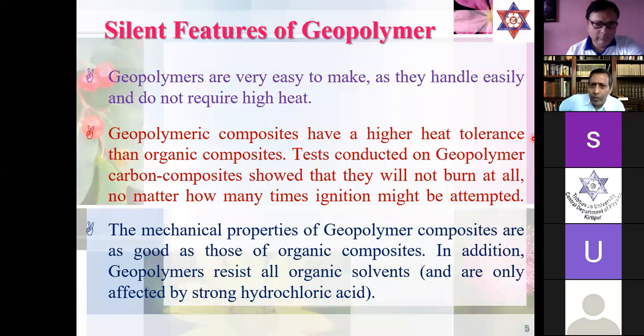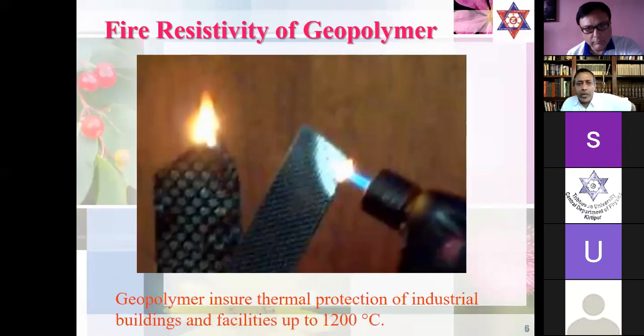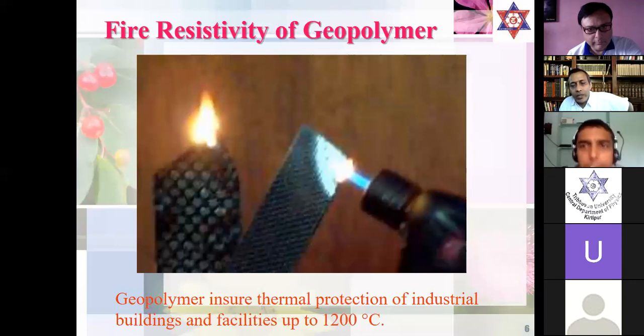These geopolymeric composites have a higher heat tolerance than organic composites. Tests conducted on geopolymer carbon composites show that they will not burn at all. I will show some pictorial examples, and the mechanical properties of geopolymer composites are as good as those of organic composites. In addition, geopolymers resist all organic solvents and are only affected by strong hydrochloric acid. So this is one example of high resistivity of geopolymers. I just want to show here that geopolymer ensures thermal protection of industrial buildings and facilities up to 1200 degrees Celsius.